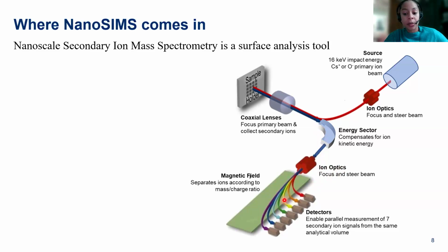And in the NanoSIMS, we have 7 detectors, 6 of which are movable, and we can detect 7 secondary ion signals from the exact same analytical volume. And then we can raster over that sample, and then we can build up an image. And this characterization tool is destructive, so we'll remove one plane of material, and then we can analyze the plane beneath it. And from that, we can actually build up a series of images, as you will see.